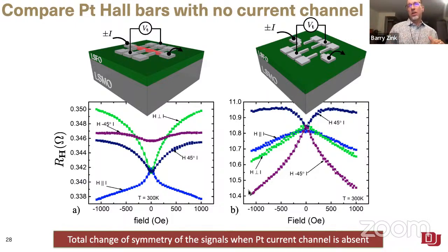So now, again, we have the most dramatic things happening at 45-degree angles, but this picture on the right, if you stare at it, looks like a combination of planar Hall effects, where you get these large 45-degree angle features, on top of maybe some background longitudinal magnetoresistance that isn't perfectly canceled off by our geometry. These are the sorts of things you expect from a conducting ferromagnetic material. So this stuff on the right is most likely dominated by kind of boring, understood things.